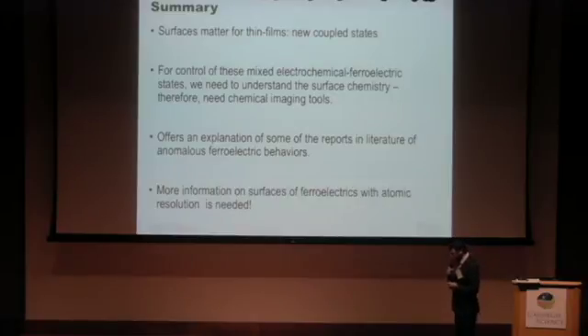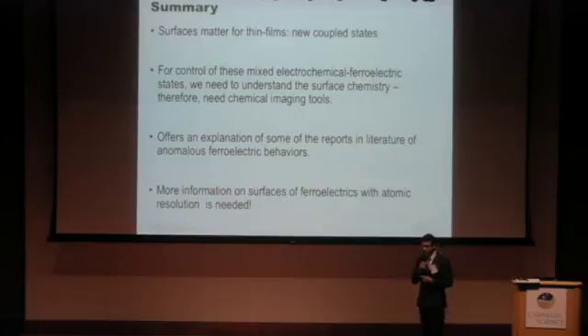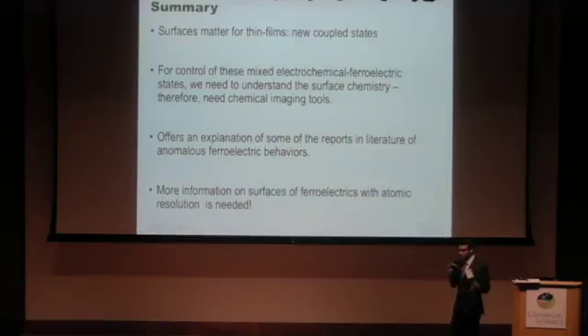So our time-resolved Kelvin probe force microscopy experiments suggest that there can be some really fast processes that occur and some rather slow ones. So it might be on the order of seconds for long ones, so you could take, for example, lateral electrodes, bias them, and see the transport of charged species from Kelvin probe force microscopy studies, and they clearly show slower timescales. But in general, if there are faster processes, and I assume that there are both fast and slow processes here, our KPFM studies can only go down to, let's say, a few tens of microseconds. So if it's anything below that, at a really local scale, we won't be able to measure it, not with our existing techniques.